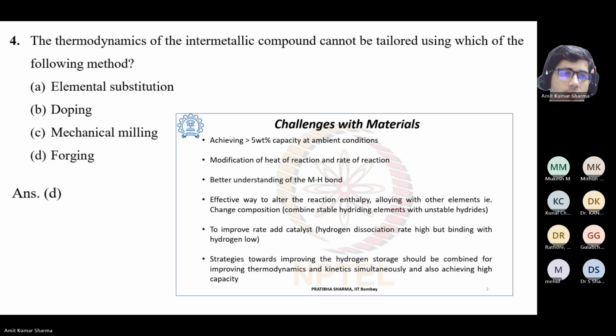Now, we will go through these methods. So, what are the challenges with materials? One is achieving 5 weight% capacity at ambient condition. Then the modification of heat of reaction and rate of reaction, and a better understanding of the metal hydride bond. An effective way to alter the reaction enthalpy is alloying with other elements, like change of composition, then combining stable hydriding elements with unstable hydrides, as we have seen in our previous slide, and improving rate with catalyst. Strategies towards improving hydrogen storage should be combined for improving thermodynamics and kinetics simultaneously and also achieving high capacity. So these are the challenges we are facing with materials.